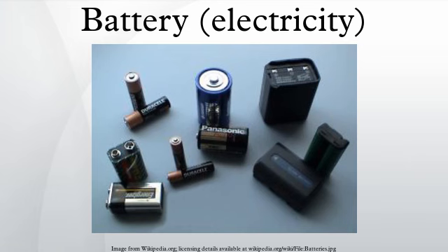Storage: battery life can be extended by storing the batteries at a low temperature, as in a refrigerator or freezer, which slows the side reactions. Such storage can extend the life of alkaline batteries by about 5%. Rechargeable batteries can hold their charge much longer, depending upon type. To reach their maximum voltage, batteries must be returned to room temperature. Discharging an alkaline battery at 250 mA at 0 degrees Celsius is only half as efficient as at 20 degrees Celsius. Alkaline battery manufacturers such as Duracell do not recommend refrigerating batteries.